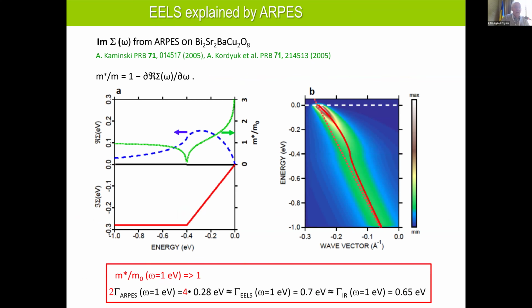Now, when you take ARPES data, for example, those from Sasha or from Adam Kaminski, then you see at low energy a linear increase of the scattering rate, which also determines the strange metal behavior in the conductivity. But at higher energy, above about 0.4 eV, it saturates. When you take this imaginary part of the self-energy and calculate the real part, then you get this green curve here, where at zero energy you have a divergent effective mass, but when you go to high energy, then you get an effective mass of 1.